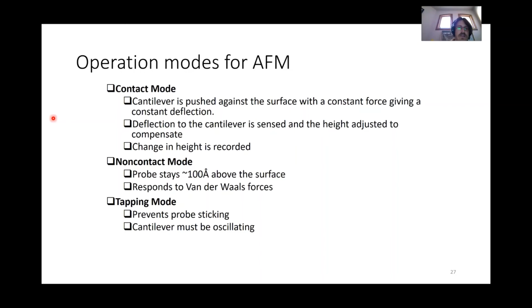Operation modes. This is the big deal for AFM. So contact mode: the cantilever is pushed against the surface with a constant force, giving constant deflection. The deflection of the cantilever is sensed and the height is adjusted to compensate. And so that change in height is what you measure. Non-contact mode: the probe's really close to the surface, okay? This is not tunneling because you're not applying a current to the tip. So that's a big difference between AFM and scanning tunneling microscope: you're not applying a probe current in an AFM. Here, the probe stays roughly 100 angstroms above the surface, and it's responding to van der Waals forces. So it's going to move, and that movement is detected by the laser system.